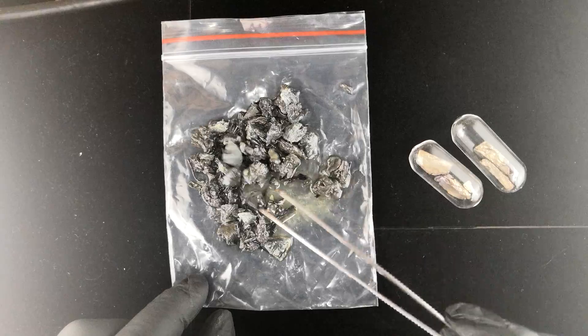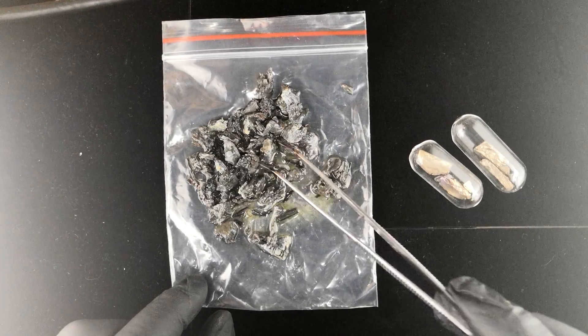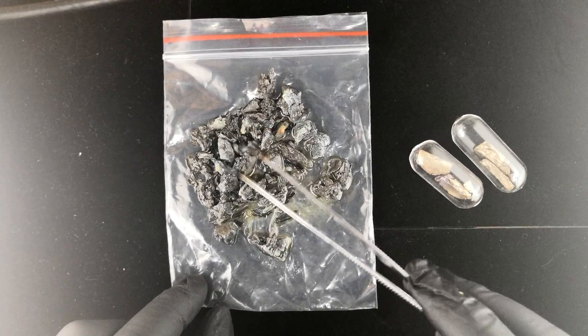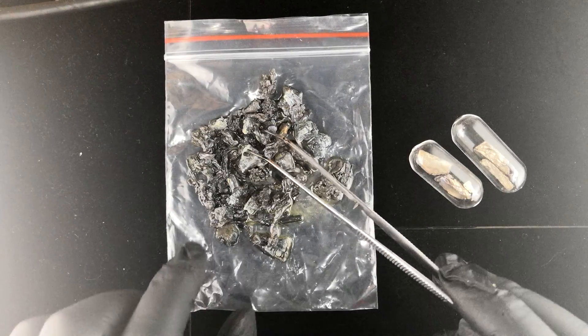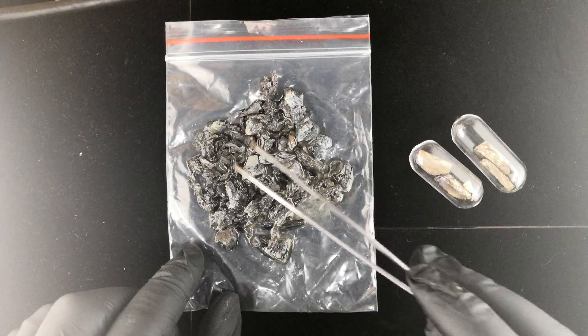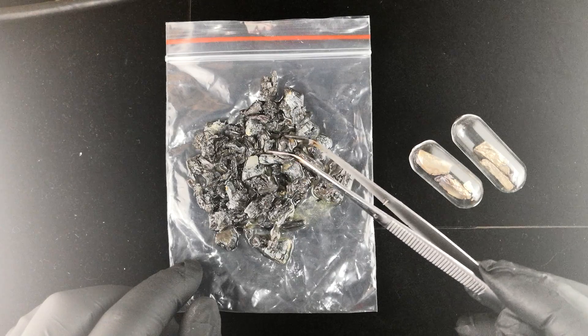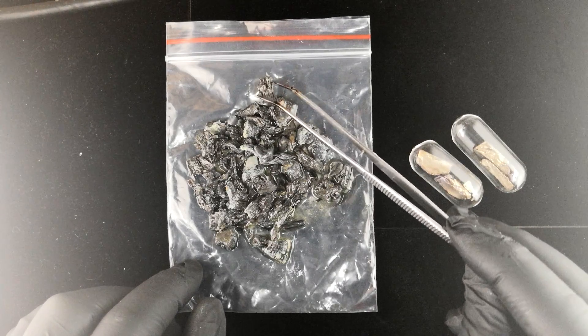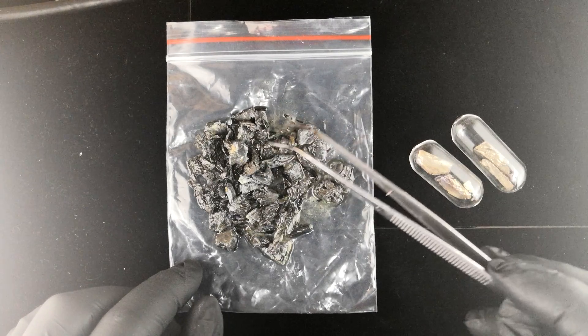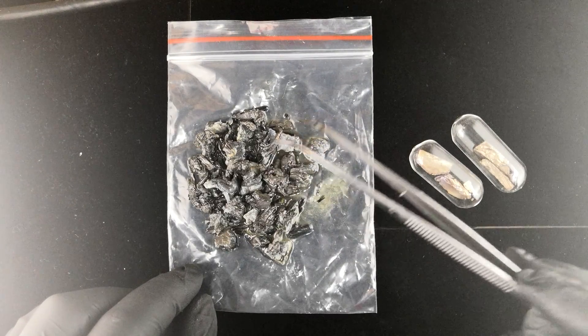This is stored in oil, and even the oil gets all slimy and yellowish. Even in oil, it continues to degrade. When this came out of the factory, it was shiny briefly, but even in the oil it continues to degrade. How is that possible? Well, the fact is that oil is permeable to oxygen, and small amounts of oxygen still get inside the oil and then come in contact with the strontium metal and start tarnishing it.